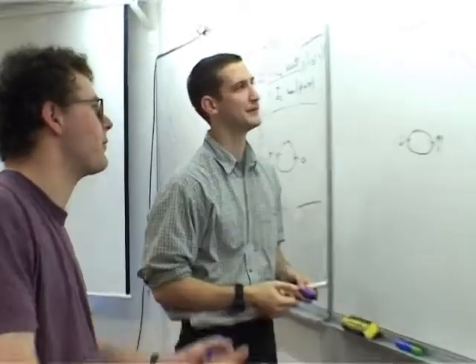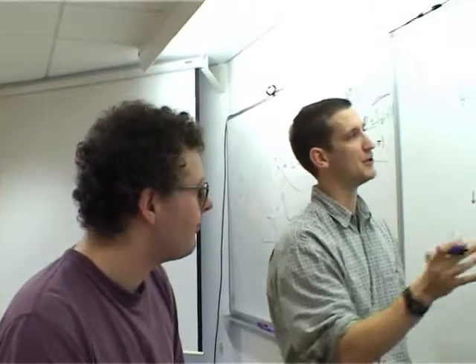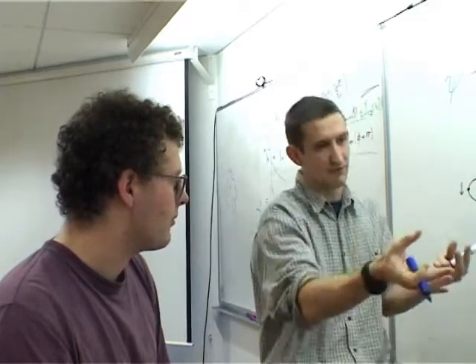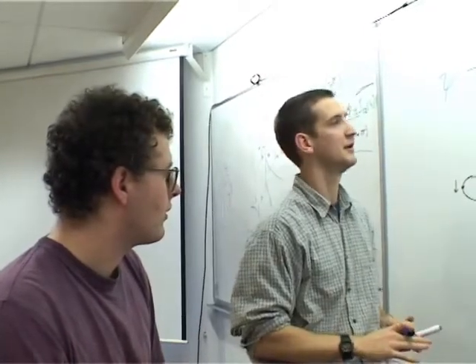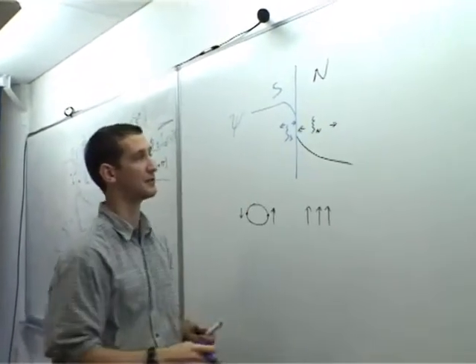What sort of numbers are we talking about here? In a normal metal, if you have a nice clean normal metal, something like copper, this coherence length can be several hundred nanometers, even upwards of microns. This can penetrate, in thin film terms, a very large distance into the normal metal.